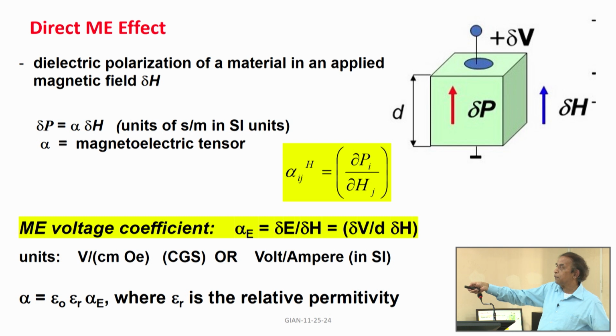And as I mentioned earlier, we measure the voltage coefficient, and that has the unit of volts per centimeter Oersted, or in the MKS system it is volts per ampere. That is because if you look at the magnitude, just look at the equation. This is in the MKS unit: delta V is in volts, d is in meters, and H is in amperes per meter. So that would lead to volts per ampere, that is the unit for the voltage coefficient in the MKS system. Otherwise, I usually use CGS, that is volts per centimeter Oersted, for the voltage coefficient.